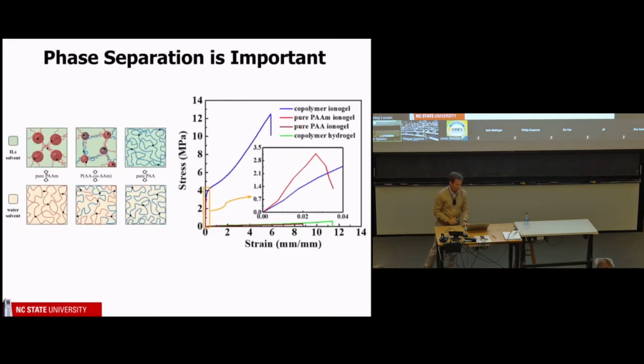So I try to depict that here. This is the contact lens material, baby diaper material, and this is them copolymerized together. This row is water as a solvent, hydrogel, and you'll see that all of them are very well solvated, the polymer chains kind of swimming around. So if you look in the contact lens material, this is the one that looked white. So what I'm depicting here are those phase-separated domains that have separated themselves from the ionic liquid. So they've kind of collapsed on themselves.